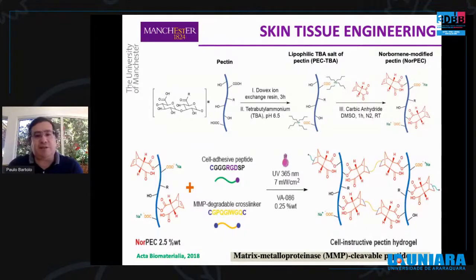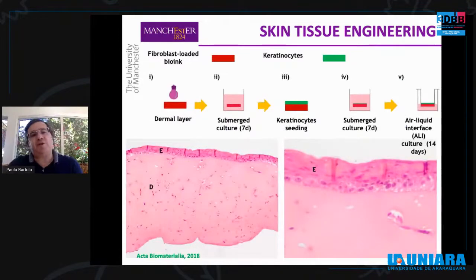And again, we decorated pectin with RGDs and also with MMPs, allowing us to gradually increase the free volume available to accommodate the cell spreading process. And then we start testing the best way to create the artificial skin, and the strategy is illustrated in this slide. So first, we print the pectin with fibroblasts. After that, we submerge the printed material in culture media during 7 days.